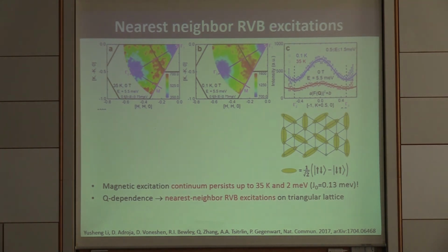So these are excitations of broken nearest neighbor RVBs on a triangular lattice. And it's really different to the excitations in the same energy range of the 120-degree ordered state or of a stripy state. And it's also very different from the excitations of RVB if we would have RVBs on further neighbors, on second, third, and so on neighbors. So to our mind, it's the first experimental realization of the excitations of the nearest neighbor RVB on a triangular lattice.